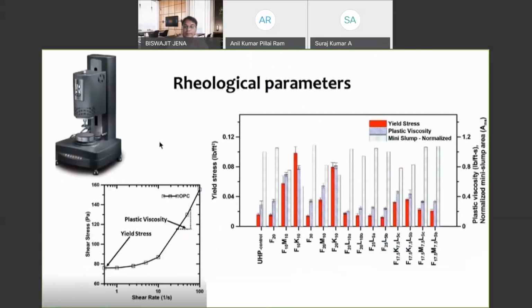Next, come to the rheology parameters. Because you want this thing to flow through a space, through dense reinforcement, you need to control the rheology. So I have done yield stress, plastic viscosity, and mini-slump, because we test through a mini-slump, as generally not all laboratories can afford a rheology test.